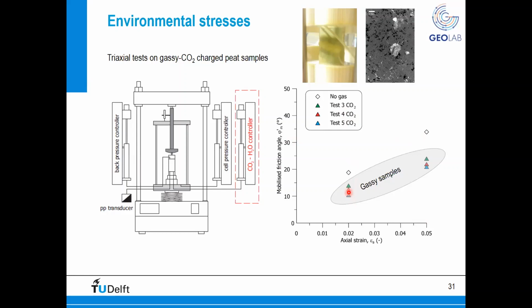And the reason is because part of the strain that you are imposing to your sample is actually used to compress the pore fluid, which now contains gas, and only a minor part will go actually in stretching your material. So accounting for the presence of climate stresses, in particular gas, is a quite new challenge that we are now facing in our environment.